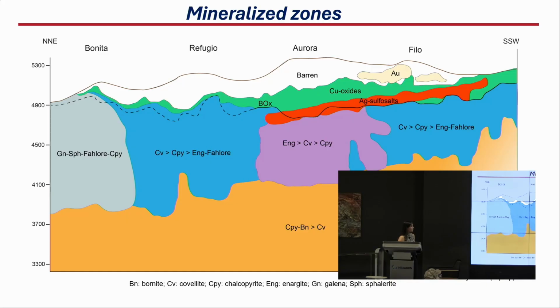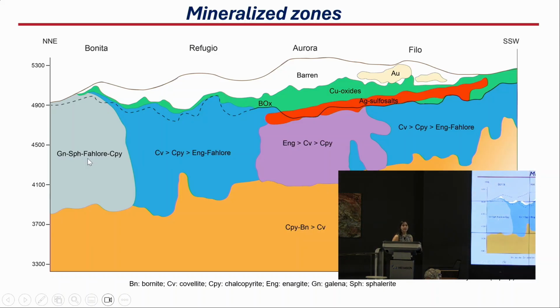On top of that, we have the silver sulfosalts manto zone, named for its tabular shape. We also have the copper oxide zone, and we have some gold, which again we don't know how it is distributed, if it's disseminated gold, maybe following the high-sulfidation model. And we have this region in Bonita mainly, which is base metal rich: galena, sphalerite, and fahlore.